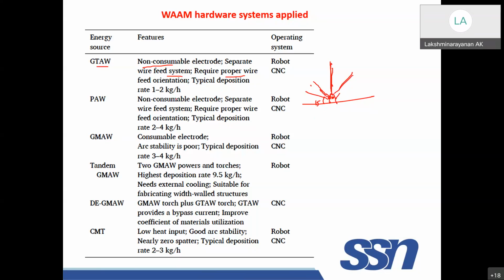Okay, so again plasma, same thing. Since it is a high energy density process, the deposition rate is somewhat higher, 2 to 4 kg per hour. GMAW is very high, because the deposition rate will be 3 to 4 kilograms per hour, since you will be using a consumable electrode. That's why the production is very high. You can also use tandem GMAW, two torches and two power sources. The deposition rate, if you see, is much higher, 9.5 kilograms per hour.